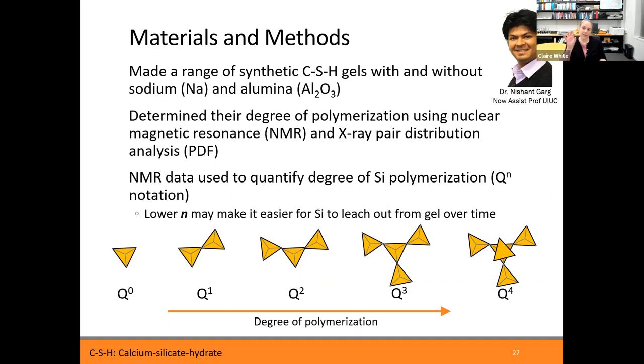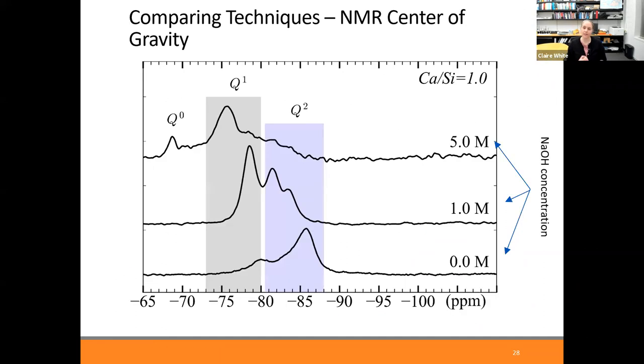So for a silica unit, silicon bonded to four other oxygens, that silica unit in these gels could be standalone. It might not be bonded to another silica unit. It might have calciums around it instead, for example. Or it could be bonded to one other silica unit. It could be bonded to two. It could be bonded to three. Or it could be bonded to four. And so this is known as Q notation, where you go from Q0 up to Q4. Q4 is the most polymerized the silica can be. Q0 is the least polymerized the silica can be. So we can quantify this using nuclear magnetic resonance. And this is what's done on this slide right here. There's the chemical shift on the x-axis.